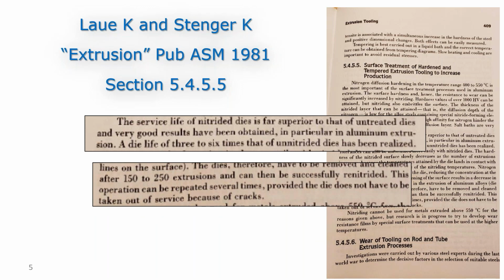And the other quote from that section is: the dies, therefore, have to be removed and cleaned after about 150 to 250 extrusions, and then can be successfully re-nitrided. This operation can be repeated several times, provided the die does not have to be taken out of service for cracks. So that pretty much defined things, and I think 1981 was a big year for you, wasn't it, Yaya?